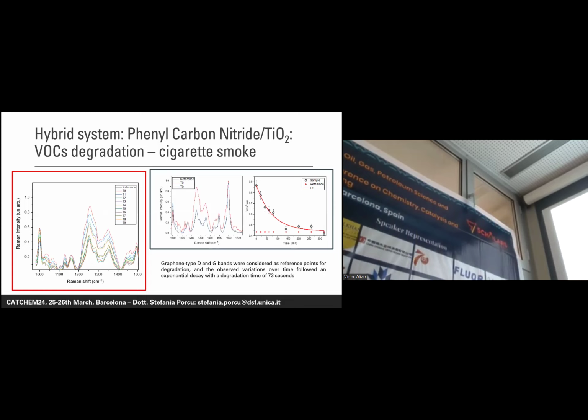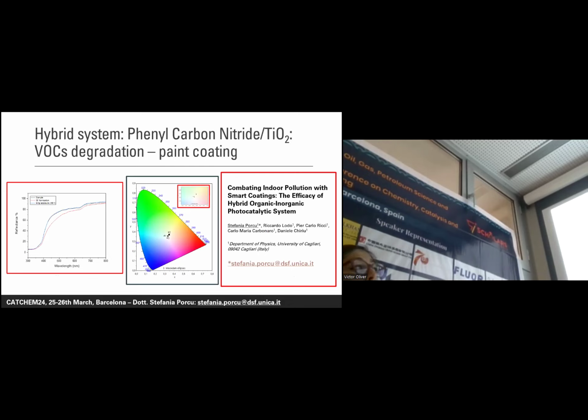I have to say that Raman analysis is a punctual analysis, so we did the measurements in different parts of the surface and then averaged the results, while reflectance measurement is a surface analysis in which you can cover a bigger part of a surface. Due to these very interesting results, we are thinking about applying this material as a coating for paints, because we saw that it remains always active for multiple cycles. We did a quick test, which is still under study, by covering a layer of paint with a coating made with our material. We observed that it works for the degradation, even in the case of smoke.